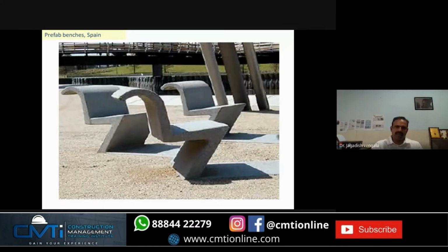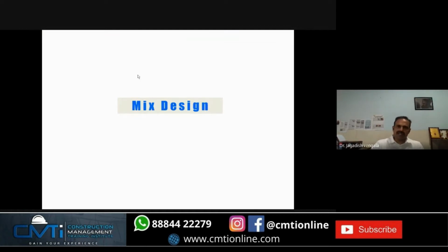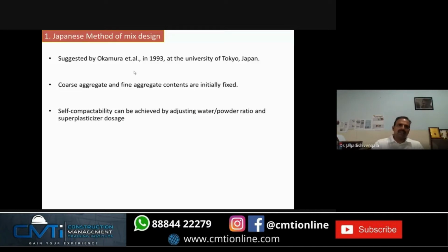Coming to the mix design, I'll just give you a small glimpse quickly. I'll run through the two methods I'm explaining. One is the method which we developed, and the other is the method by the Japanese, suggested by Okamura et al. in 1993. This is the first method that came from the University of Tokyo, Japan. In this method, you have to fix coarse and fine aggregates initially. By adjusting the water powder ratio and superplasticizer dosage, you get the self-compactability.